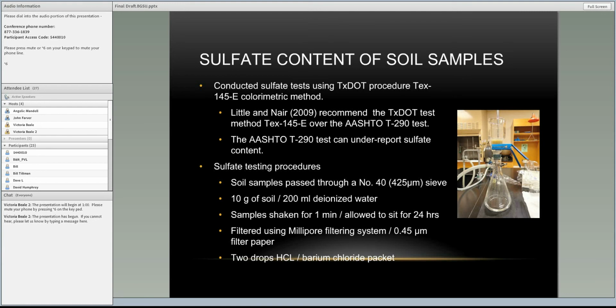In our sulfate test procedures, we passed the soil through a number 40 sieve. Then we took 10 grams of that soil and mixed it with 200 milliliters of deionized water. We shook it really vigorously for 1 minute and allowed it to sit for 24 hours. It was then filtered with a Millipore filtering system, which you can see over to the right there, and we used a 0.45 micron filter paper.